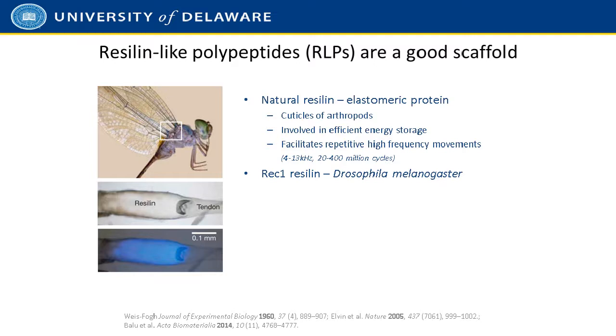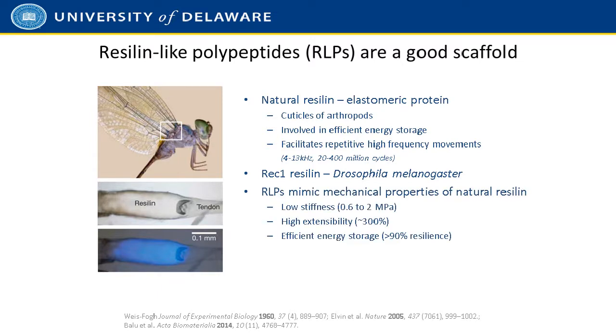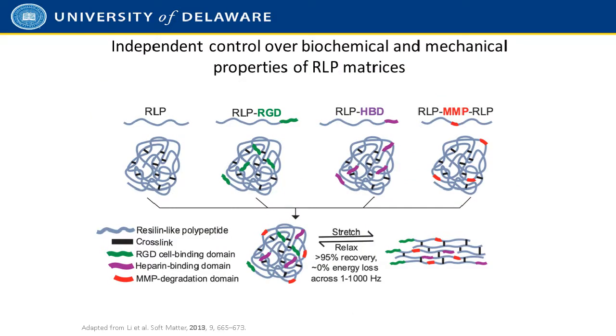REC1 resilin from fruit fly, the gene sequence for encoding that material has been known now for 15 years, and it allows us to make mimetic materials where we can control and change the amino acid sequences slightly to make resilin-like polypeptides that mirror the natural resilin properties. So we can make materials that are low stiffness, high extensibility, and very efficient energy storage. Because of the sequence control that we have of these materials, they can undergo both the upper critical solution temperature transition and the lower critical solution temperature transition as well.